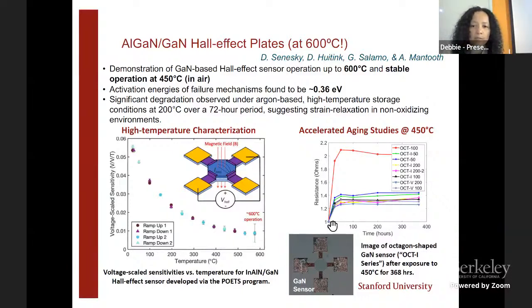So this is what you see here. This is time. Sorry. Holding at 450 degrees Celsius, we see this burn-in period and then stabilization of the resistance. So this is telling us that our ohmic contacts are remaining stable over a period of time. And this is for a variety of our Hall effect mobility family devices. These represent different shapes of our Hall effect.